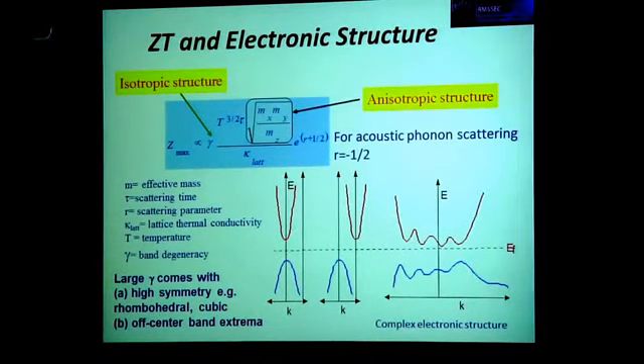So here's a cartoon of an electronic band structure, and if the symmetry is high and you have a band extrema at particular places in the Brillouin zone, you can get high gammas. For example, if you have cubic structures, rhombohedral structures, and so on. But at the same time, if you have complex electronic structure, where it gives you multiple pockets, say, in the conduction band, in red, or multiple hole pockets in the valence band here, that gives an additive effect. In other words, every pocket contributes its own thermal power, its own thermoelectric activity, and it's additive. And then, if it's high symmetry, then it's multiplicative because the gamma can be high.